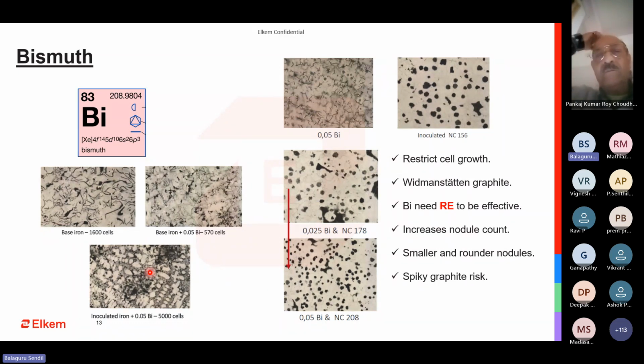That is why we still have bismuth-based inoculant in the market, which ensures that it breaks a big nodule into small ones and then improves the nodule count. So this is the logic in which bismuth can be taken a benefit for ductile iron when it is combined with rare earth, and in gray iron, it is quite challenging. So this is with respect to the bismuth. The source of bismuth, again, can come from scrap as well.